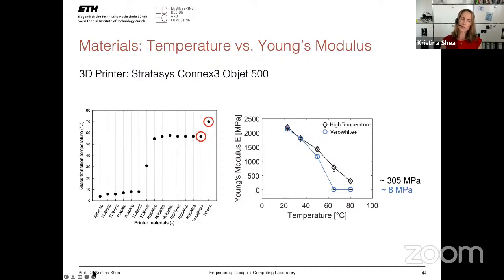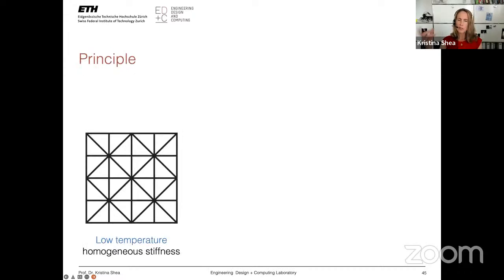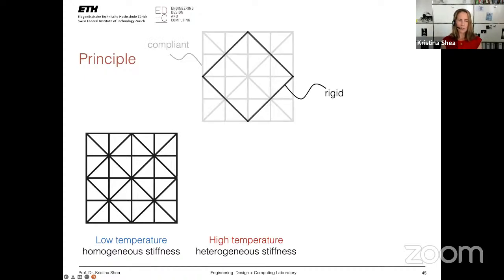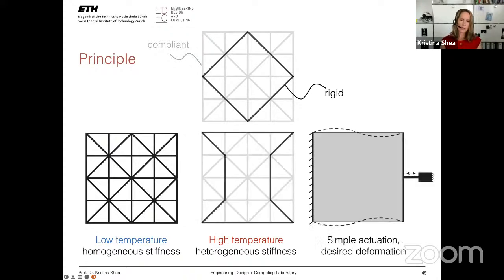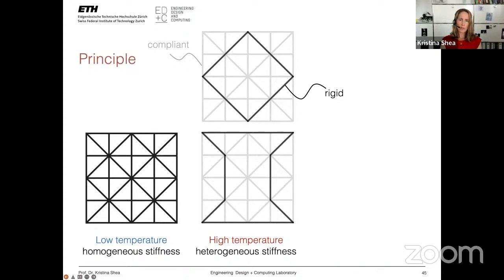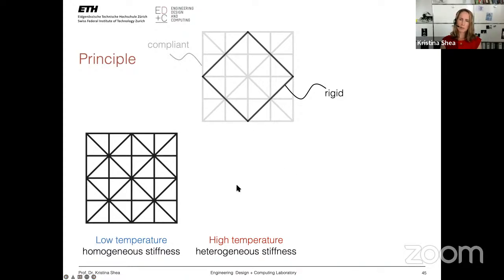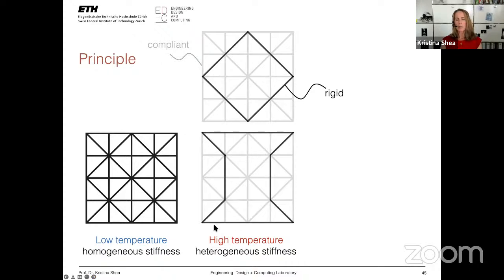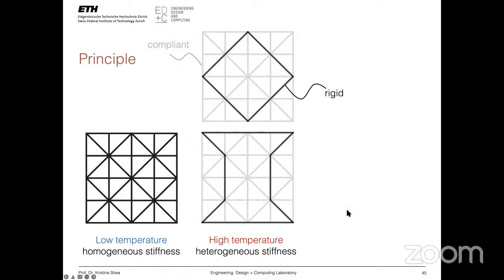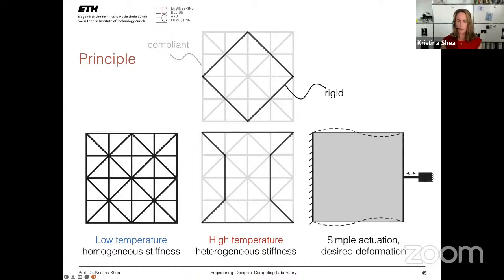So it's significantly different. And so he wanted to get rid of this programming step that was needed for the bistable actuators that Tim had. So what he thought of is, okay, if we have a lattice structure and it's at a low temperature and we have a homogeneous stiffness, then what happens if we add in some compliant members and some rigid materials? In this case, we can then heat it up, and then we get heterogeneous stiffness. In the heterogeneous stiffness, the structure will deform. So we apply a load, and then we get simple actuation and a desired deformation, without programming individual members like you saw previously. So that was the goal.